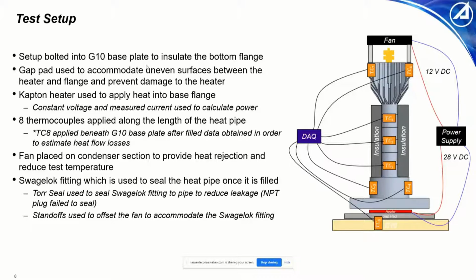The goal was just geometry, not to add any insulation. We used a Kapton heater to apply heat into the base of the flange using a constant voltage and measured current to specify different power values.